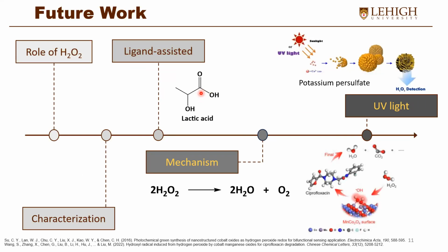However, the role of the hydrogen peroxide is not clear. It's because the particle size is too small, so the XRD peaks are too broad. I need to continue to try more experiments, such as different amounts of the hydrogen peroxide and different amounts of the sodium hydroxide.